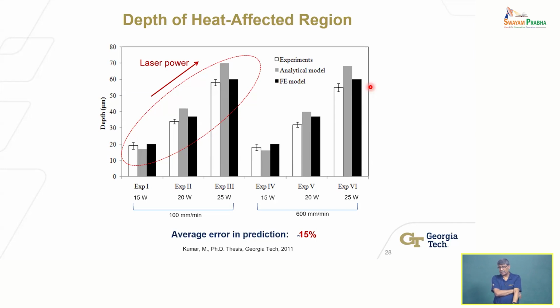There is no rake. There's no cutting here. There is absolutely no cutting. I'm just scanning. There is no cutting at this point, right? This is only scanning the surface with a laser. Interaction time is less. Exposure time is less, right? So therefore, obviously, the mechanism by which heat is transmitted is through conduction, okay, when laser and matter interact. And so yes, you're right that it is less, and it's less because at higher speeds, lower temperatures are produced because of lower interaction time, okay?